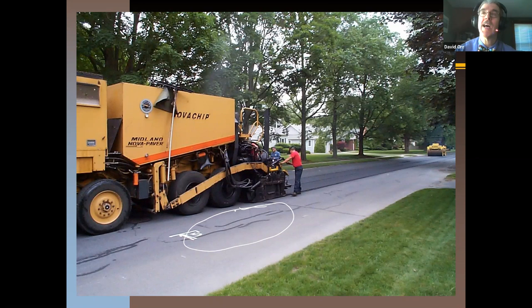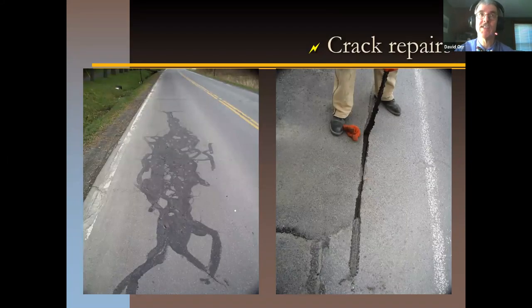As a minimum, I like to see at least a month, really a season, is the way I think about it. So you need not only time for it to cure out, but to also see, did you get everything? So if I was going to be paving now, I would want to have done that probably in April. And actually March and April, if the weather is dry, is some of the best time to actually do crack repairs if they're moving. And the key with crack repairs is pick good candidates. Just like paving, pick good candidates and do them well.